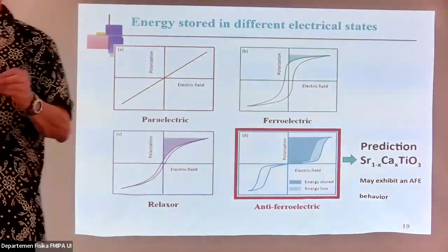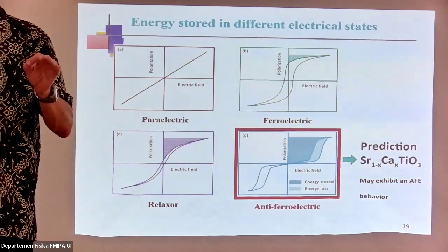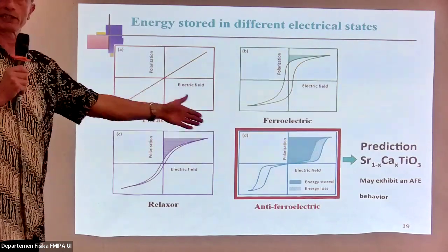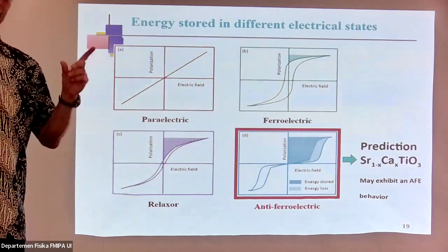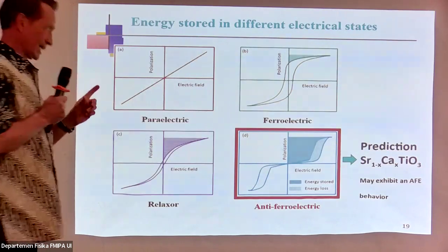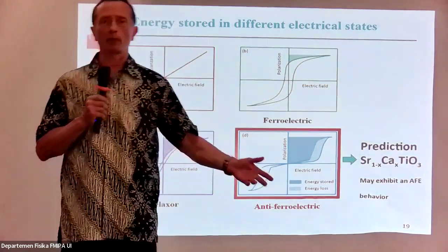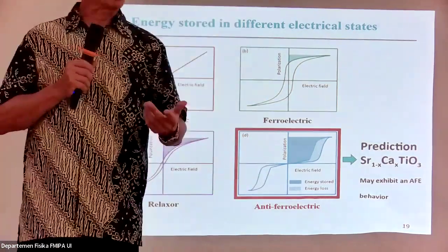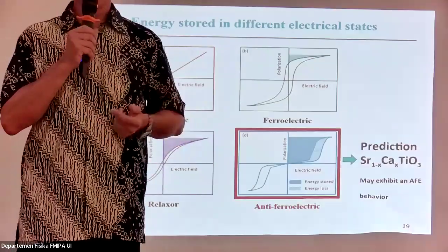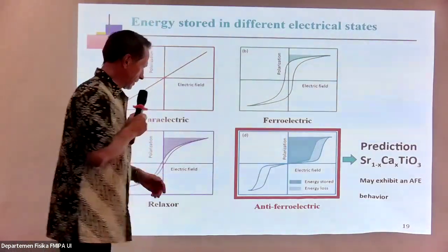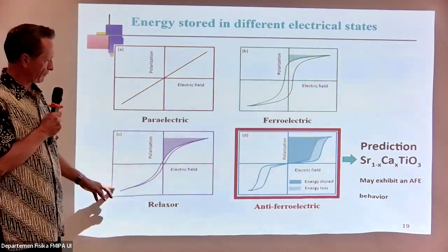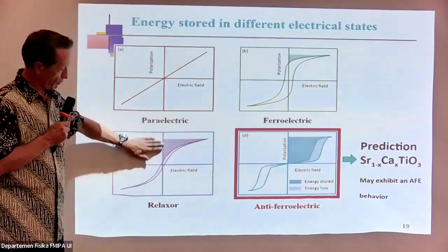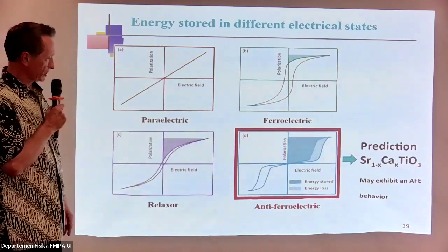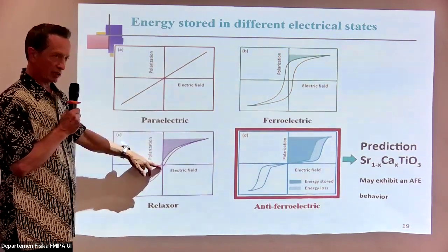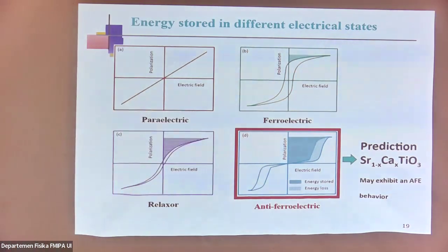The problem with this family is that in this world, we have very few materials which present this famous antiferroelectric cycle, and most of them are lead materials. They contain lead. That's why I don't work with this family, because I dedicated all my studies during my career to lead-free materials. So currently, I mainly work with relaxors, which present a very important area for storage. And of course, you can combine the dielectric behavior with relaxor behavior. This is my new trend for my new studies.